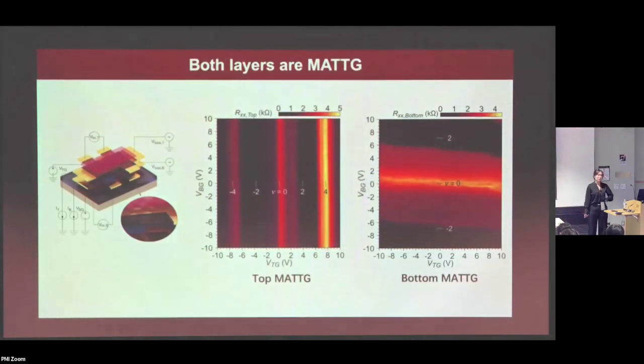The very first thing you want to do when you make this kind of very complicated structure is to check that you actually made the structure that you thought you made. So here are the resistance maps for the top and bottom magic angle twisted trilayer graphene as a function of bottom gate and top gate voltage. You can see all the features that are common in magic angle graphene: trigonal distortion, potential superlattice features, and most importantly, these very dark regions of zero resistance, which is the superconductivity, and that's happening in both of the layers. So with this, we can confirm that we made the structure that we thought we made.